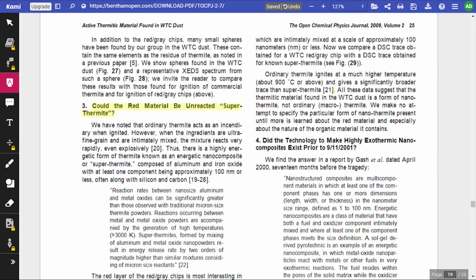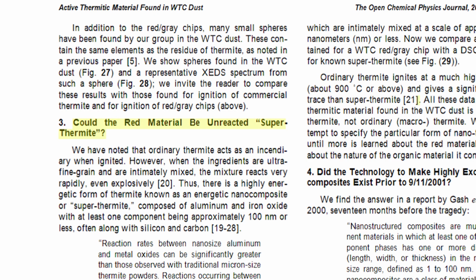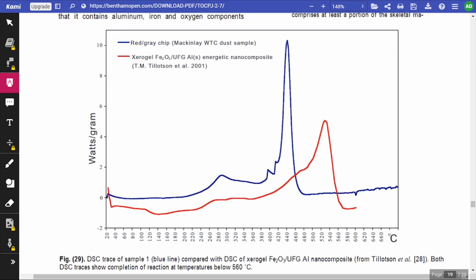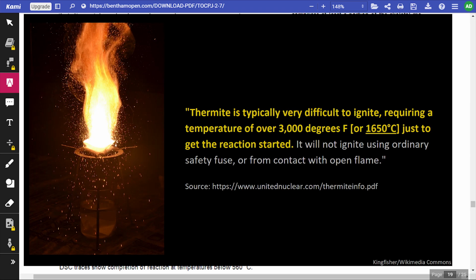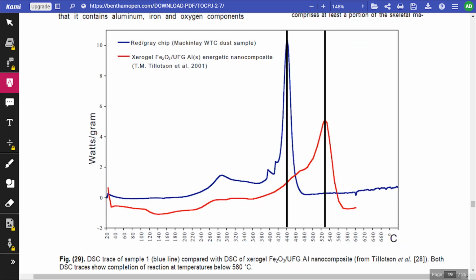They try to explain this discrepancy in the paper by saying, but this is no ordinary thermite here. The material that they used was super thermite. Then they compare the DSC graph from the red-gray chip against one that was obtained from some so-called super thermite. As we can see, the super thermite reaction peaks at about 530 C, which while yes, much lower than conventional thermite, is still 100 C hotter than the peak ignition temperature of the red-gray chips.